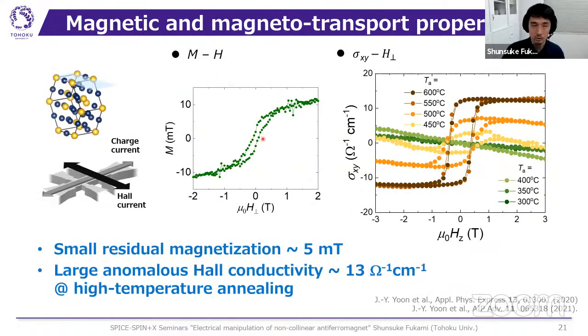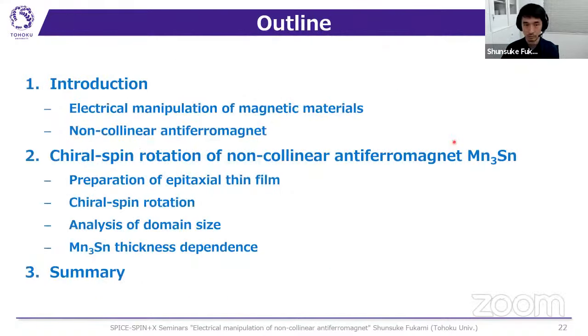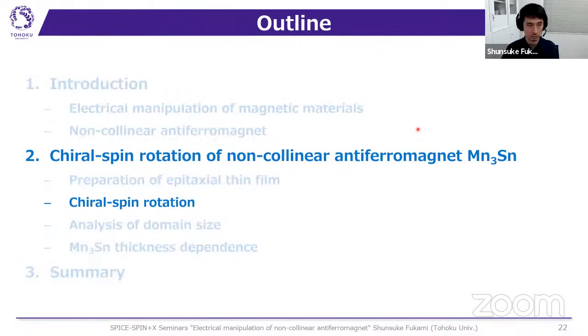Okay, so next, let me show the magnetic and magnetotransport properties. This shows the MH loops measured by the VSM. We see a very small residual magnetization of around 5 milliteslas, but we observed a very large anomalous Hall conductivity of up to 13 ohm inverse centimeter inverse when we annealed the sample above 550 degrees Celsius. Okay, so we now have the nice epitaxial thin film. So next we prepared the device to observe the chiral spin rotations.